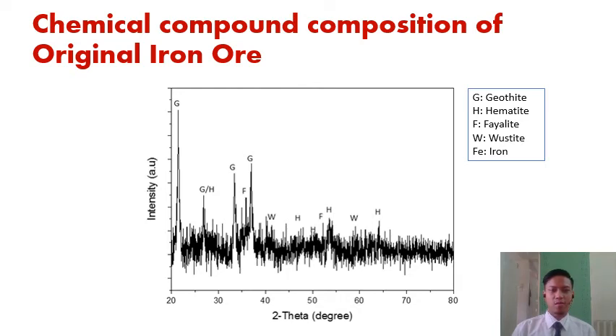This is the chemical compound composition of the original iron ore. From the XRD peak, it can be seen that the major phase of the iron consists of goethite, which is common in local iron ore due to its high water composition, followed by the second highest measuring peak consisting of hematite and also fayalite and wustite.